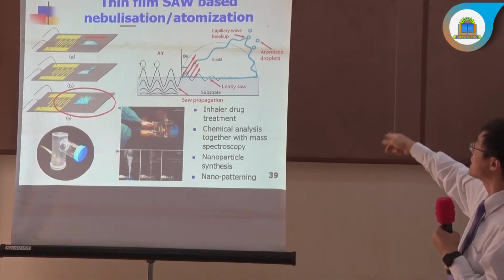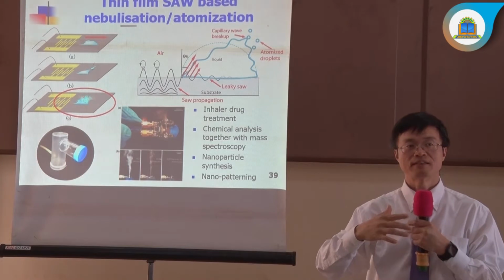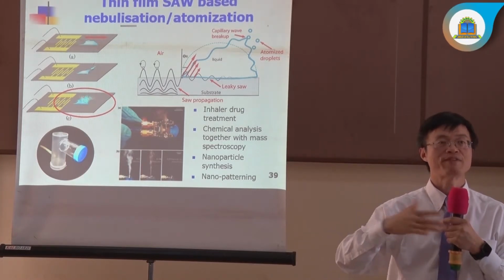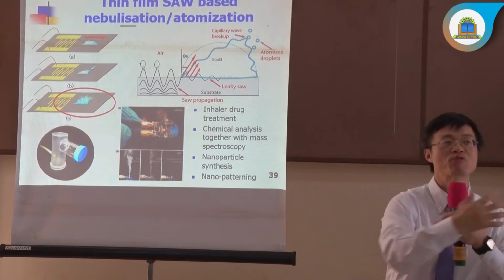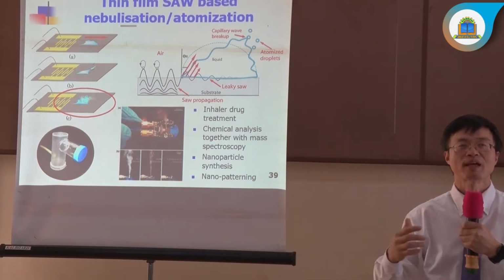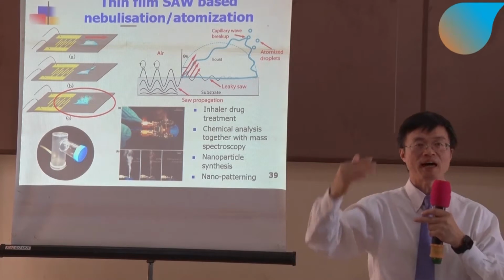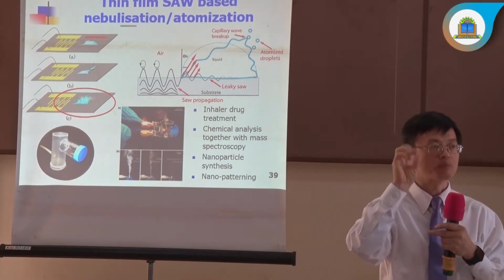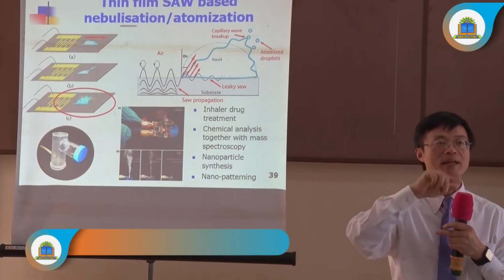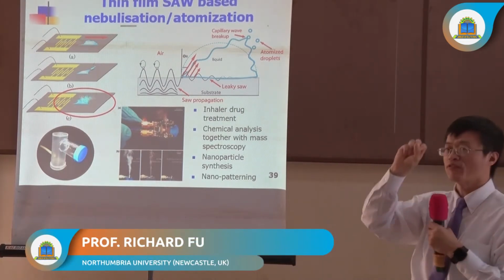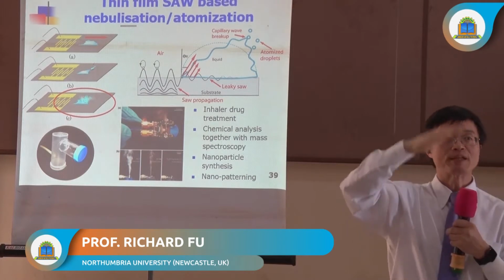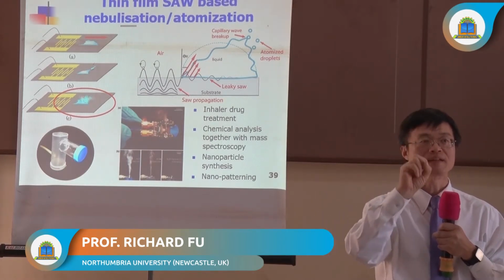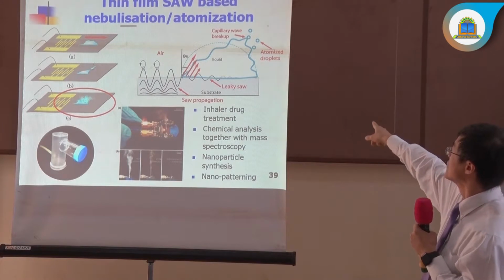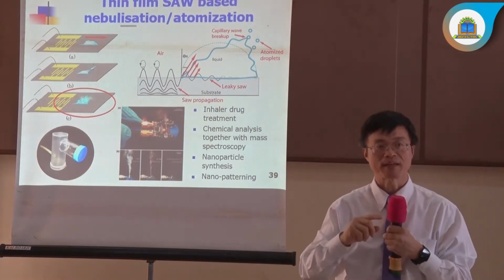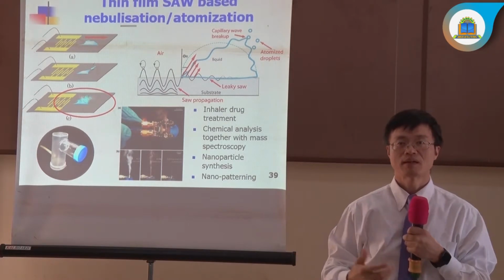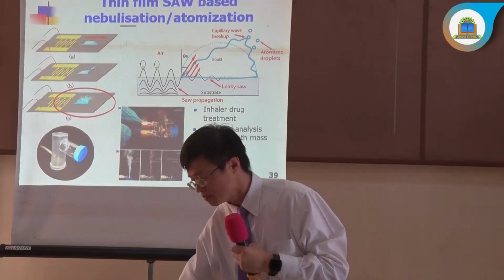Surface acoustic wave propagates into the liquid. In this case, the surface is not hydrophobic, it's hydrophilic, so the liquid won't move freely. Then the surface vibrating on the droplet generates small capillary waves. Capillary waves are very small waves on the surface. If the amplitude becomes larger and larger, then small droplets are ejected from the surface. So there are a lot of small atomized droplets, which become mist.